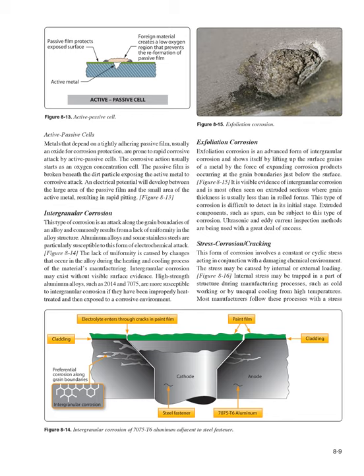Figure 8.13, intergranular corrosion. This type of corrosion is an attack along the grain boundaries of an alloy and commonly results from a lack of uniformity in the alloy structure. Aluminum alloys and some stainless steels are particularly susceptible to this form of electrochemical attack. Figure 8.14. The lack of uniformity is caused by changes that occur in the alloy during the heating and cooling process of the material's manufacturing. Intergranular corrosion may exist without visible surface evidence. High-strength aluminum alloys, such as 2014 and 7075, are more susceptible to intergranular corrosion if they have been improperly heat-treated and then exposed to a corrosive environment.